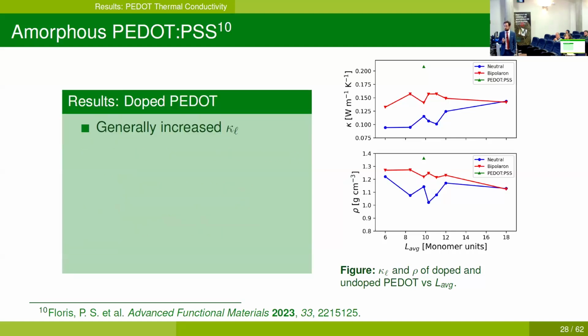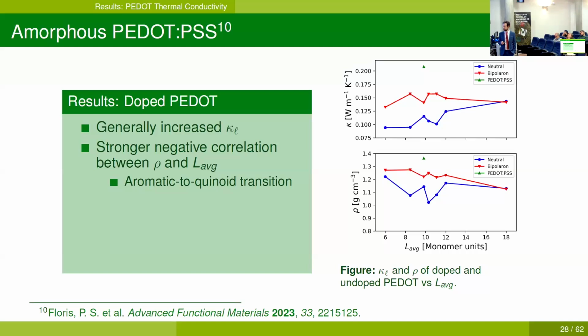When we look at the doped PEDOT, so the red line, we see that the red line is generally above the blue line, so there's a general increase of kappa L. However, the values for 6 monomers and for 18 monomers are the same, and there is actually a sort of maximum here in between around 9 and 12 monomer units. On the other hand, we see a stronger negative correlation between the density of the doped samples and the average chain length. So you see here that it's steadily decreasing with average chain length.